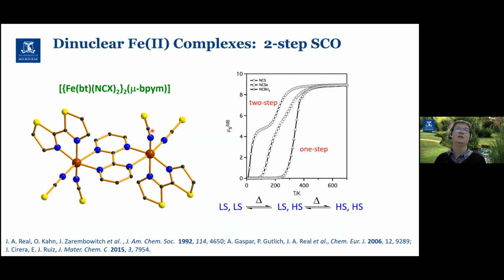So in this case, it's isothiocyanate. And by varying the terminal ligands, you can actually control whether you get a sequential spin crossover at the two iron centers or a simultaneous spin crossover. So depending on where you are, in the isothiocyanate case, you have a two-step transition where the two irons transition sequentially, and in other analogues, you have a one-step transition where they both go at the same time.